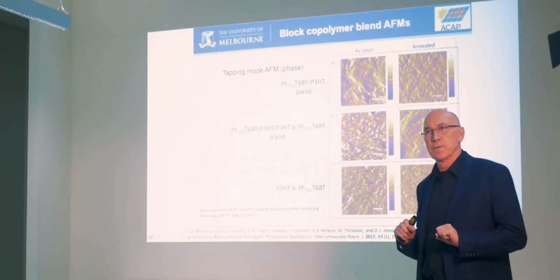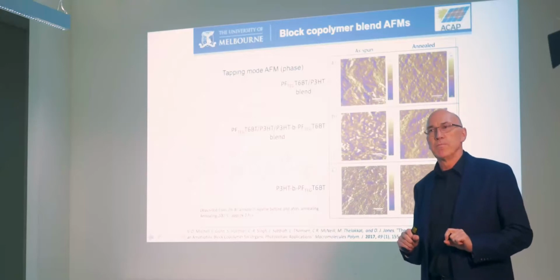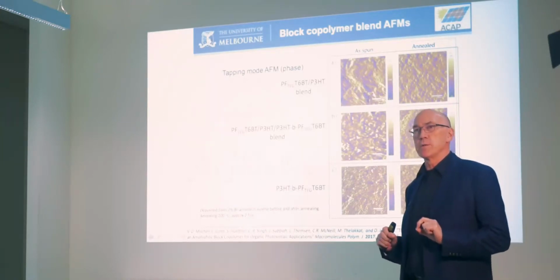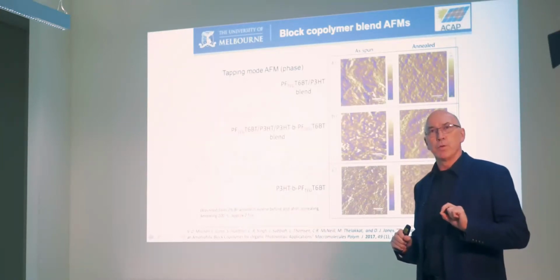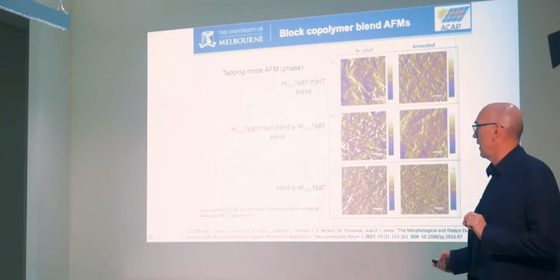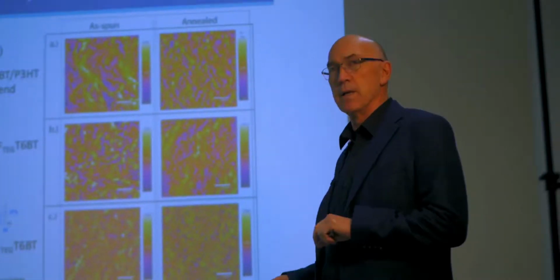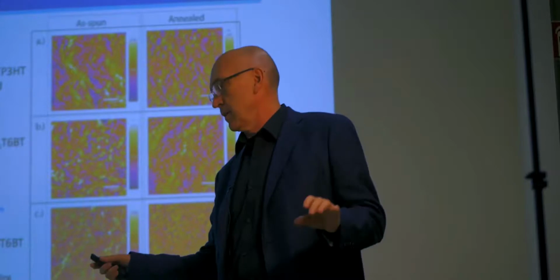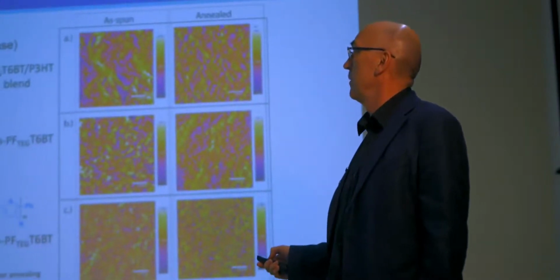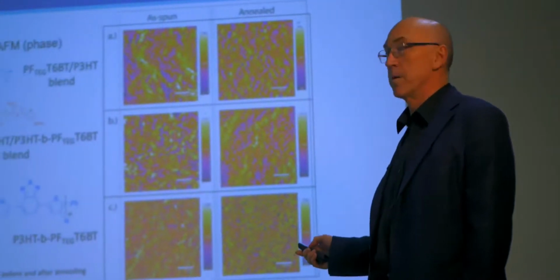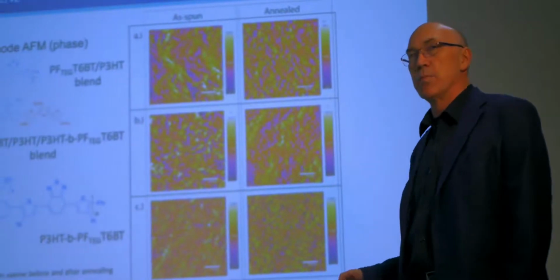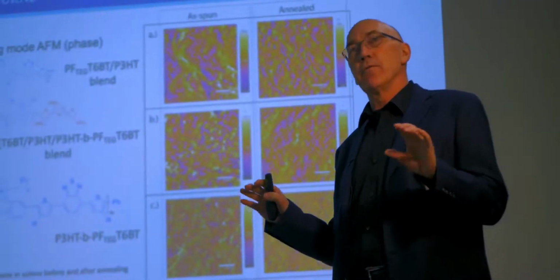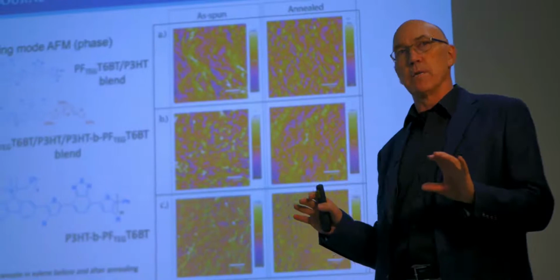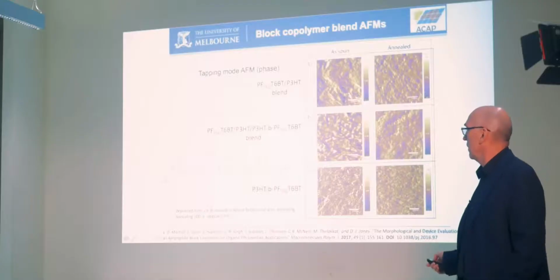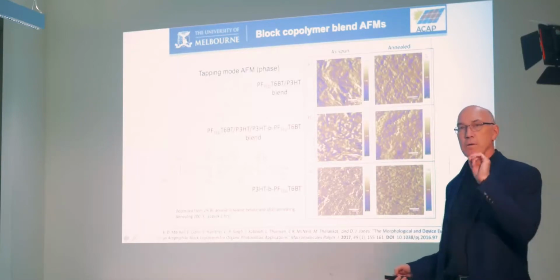these two blocks. If you look in the literature, you'll find that when people have done this work before, they don't have pure di-block copolymers. They don't have a block of A and a block of B. They've got a mixture of everything. They've got a mixture containing the homopolymer of the donor, the homopolymer of the acceptor, and maybe tri-block copolymers, and you have no idea what's going on when you actually make a device out of those. Having this handle, we were able to purify this di-block copolymer really, really well.